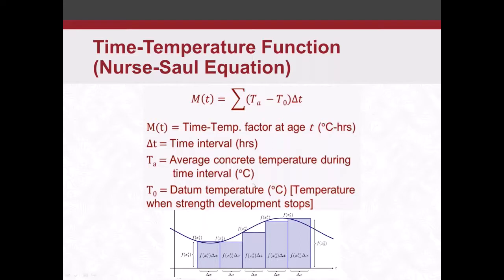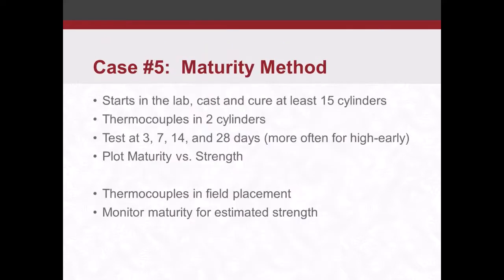T sub 0 is our datum temperature, which is essentially the temperature when strength development stops. ASTM says you can assume that to be 0 degrees Celsius, which makes sense. Ice isn't going to hydrate cement. There is a method to calculate that a little bit tighter, but it's typically taken to be 0. So we add all of these different temperatures and time intervals, and obviously that's the area under a curve, and we get our maturity function. The units are degrees Celsius and hours, or it could be degree minutes, degree hours, degree days even, but typically degree hours.